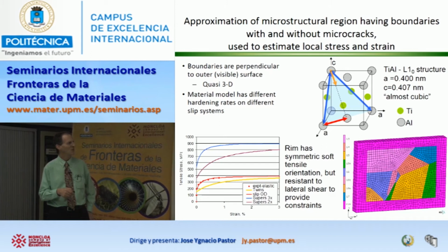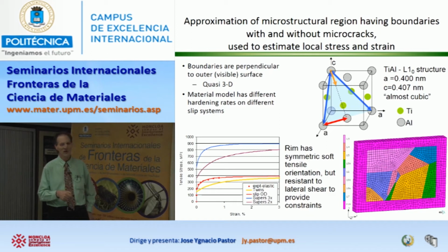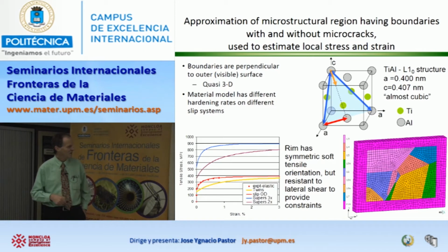And as a consequence of these being difficult, twinning, mechanical twinning, which goes in this direction, which is perpendicular to the other, is actually pretty easy in this material. And that's what gives it at least some ductility. Now, note the strain scale right here goes 1 to 2% or thereabouts.